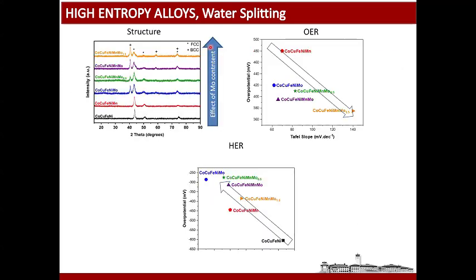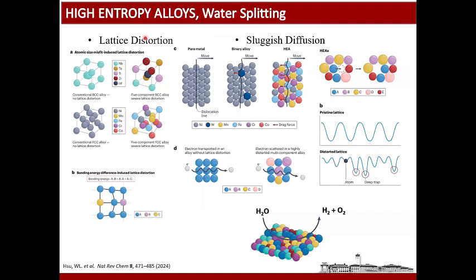So again, the effect of the molybdenum content is obvious. Increasing the amount of molybdenum increases the strain and the stress on the surface, which increases the number of active sites at the surface. So that decreases the overpotential both for oxygen evolution and the hydrogen evolution reaction. So this lattice distortion is the main effect for the increased electrocatalytic activity.